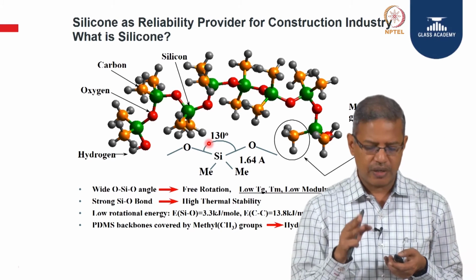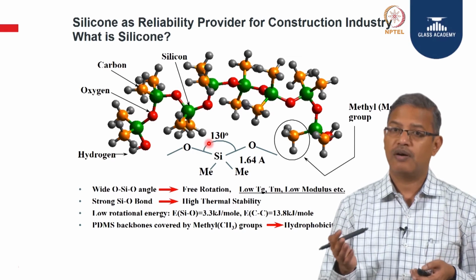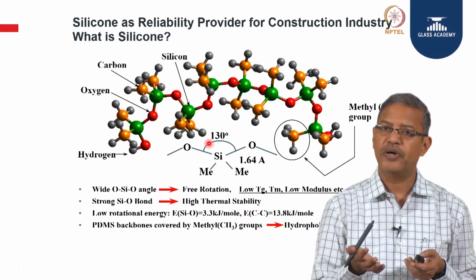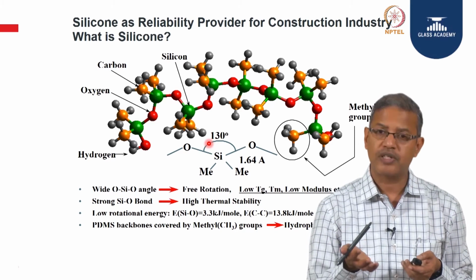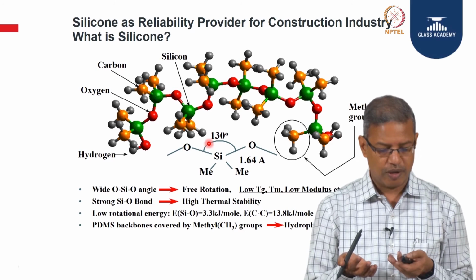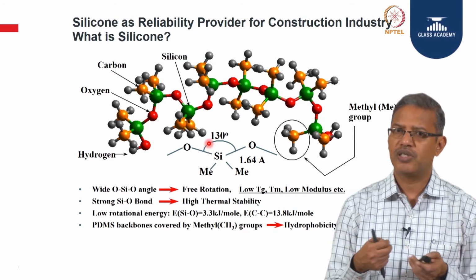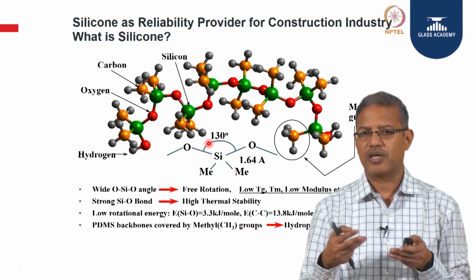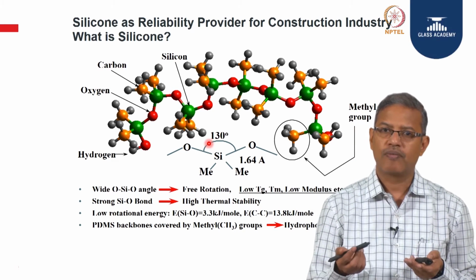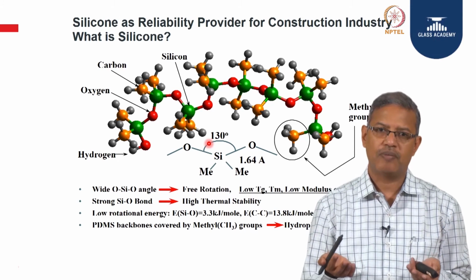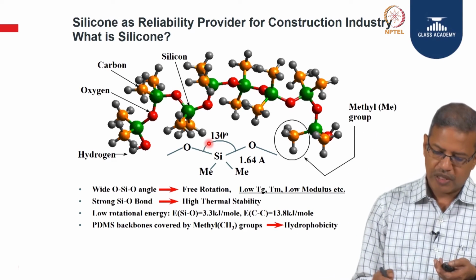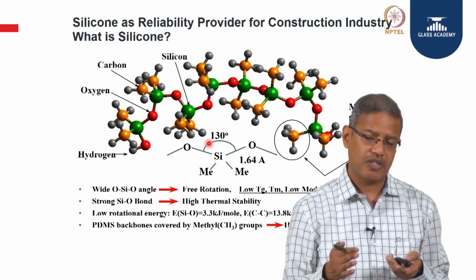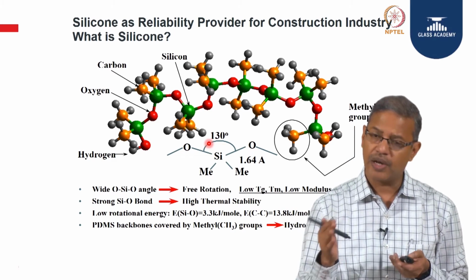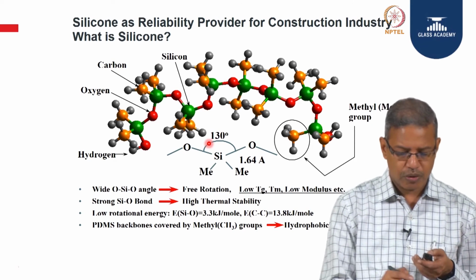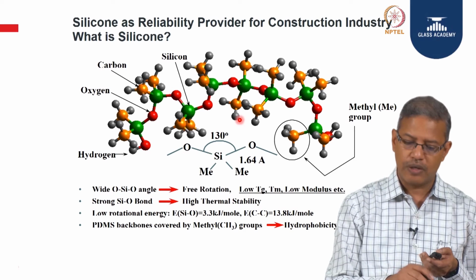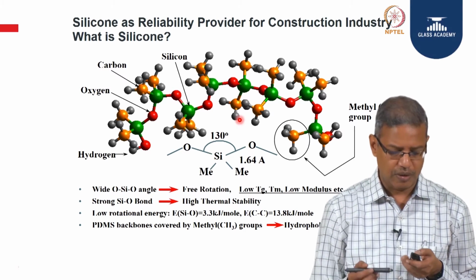In construction applications, we need to have some amount of rotation or free movement in the product to allow for thermal movements. We cannot have a system which is completely rigid, holding the glass to the frame and not allowing any movement. If that is so, then whichever is stronger will prevail, and the other one will break. So, what is important is you need a material which is tough, but also remains flexible and has good modulus to take certain movement. That is what it does with the inherent chemical structure of silicon oxygen silicon.